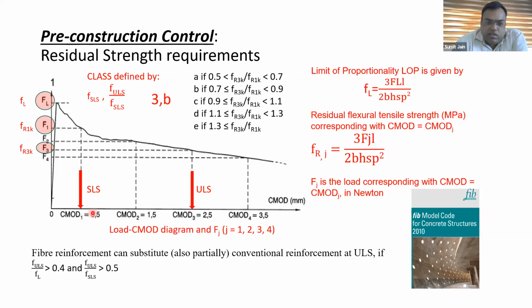And in this test, the CMOD of 0.5 corresponds to the serviceability limit state, and the CMOD of 2.5 corresponds to the ULS limit state. The respective values on the load correspond to the stresses. This is the limit of proportionality, which we call FL. FL is computed, and then we get the flexural stress corresponding to FL. Then we get the flexural stress corresponding to the SLS state, which we call FR1, and then we get FR3. So the ratio of FR3 upon FR1 is actually the ratio of ULS by SLS.